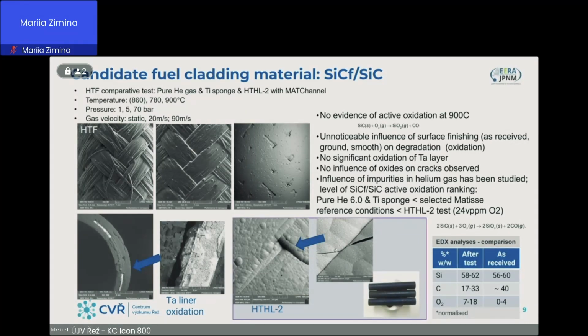We were asking how long this silicon carbide cladding shall stay in the reactor, at least 6 years, so that it would not be the case for silica oxide growth. So there is a lot to study and to develop. As I said, not only improvement of the surface composition and sealing, but also joining and coating.